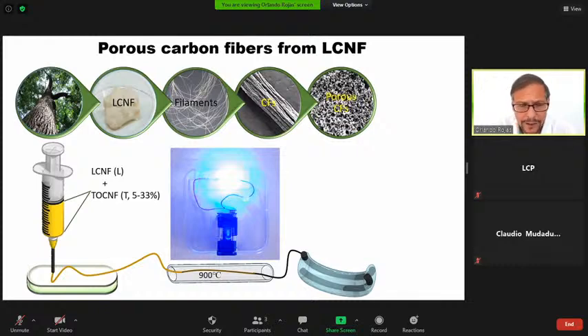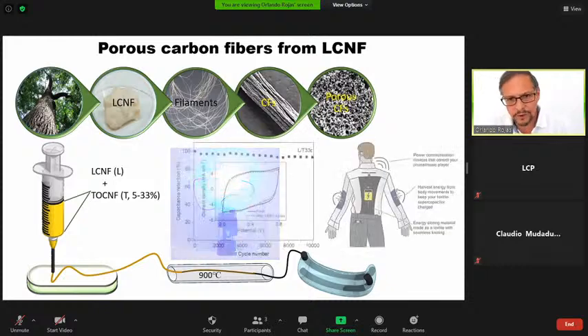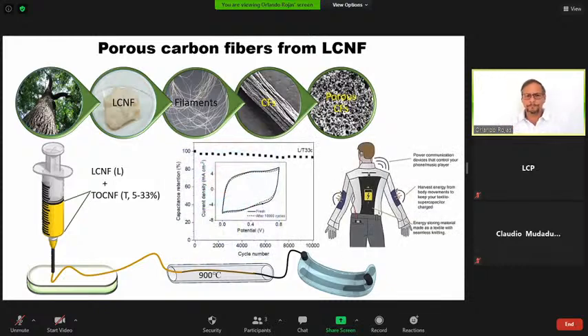It works quite nicely as a supercapacitor. But the main point I want to highlight, compared to other carbon materials, is the low temperature of carbonization. A single-step carbonization with no pre-steps is possible to produce a carbon fiber. I think this is very important when we talk about carbon fibers. It's not only the raw material, but the energy that is used in the carbonization process. And that's very, very important.